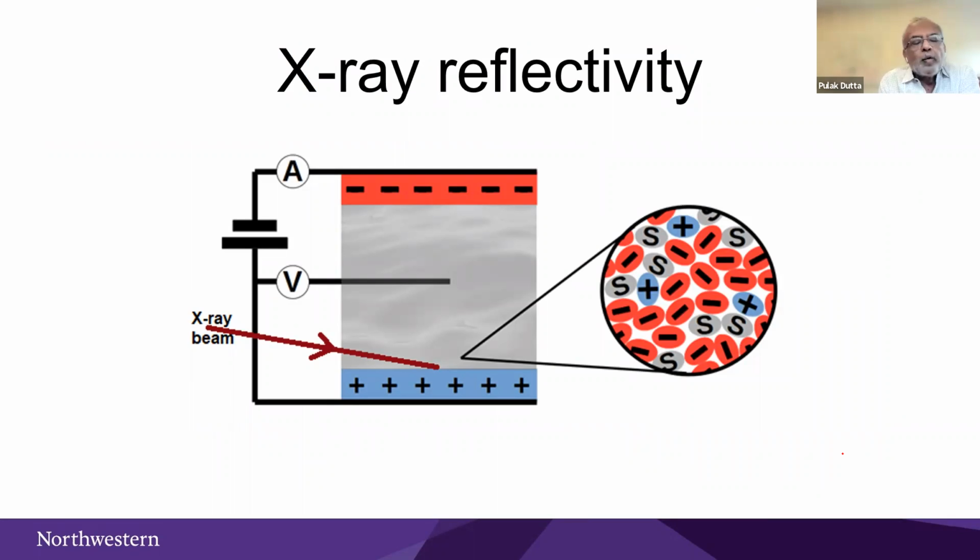The experiment we're doing is to go into an interface. We use silicon surfaces, for reasons I'll explain in a minute, with the oxide layer stripped off. So this is the RTIL. And in the expanded picture, we're going to talk about solvent. In the general case, there's solvent, there's anions, and there's cations. And the idea is, what's happening at the interface? What is the capacitance due to? And what is the general physics of structure at the interface?